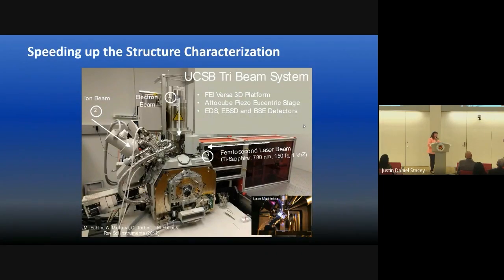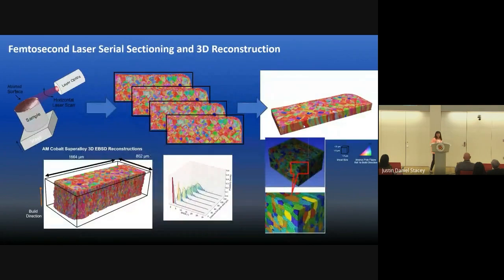So this has motivated something that we've been doing for probably the last 15 years, and it's the development of a platform that we refer to as TriBeam microscope. This is basically a focused ion beam microscope, in this case a Versa 3D from FEI. That would, of course, have an electron beam and an ion beam, and then we have taken into this chamber a femtosecond laser. You can see all the beams here, very crowded scope. The motivation for the femtosecond laser is to give us a very high throughput way of slicing large amounts of material at the resolution you need to get multimodal microstructural data.